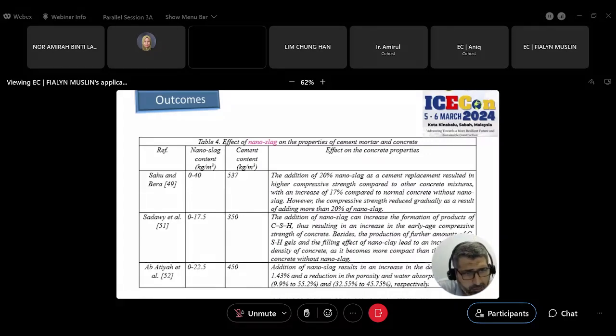Sadawi et al. also showed that the addition of nanoslag can increase the formation of CSH products, thus resulting in an increase in the early age compressive strength of concrete. Ab Atiyah et al. also showed that the use of 22 kilograms per cubic meter of nanoslag content with 450 kilograms per cubic meter of cement content, the addition of nanoslag results in an increase in the density, up to 1.43%, and a reduction in the porosity and water absorption.